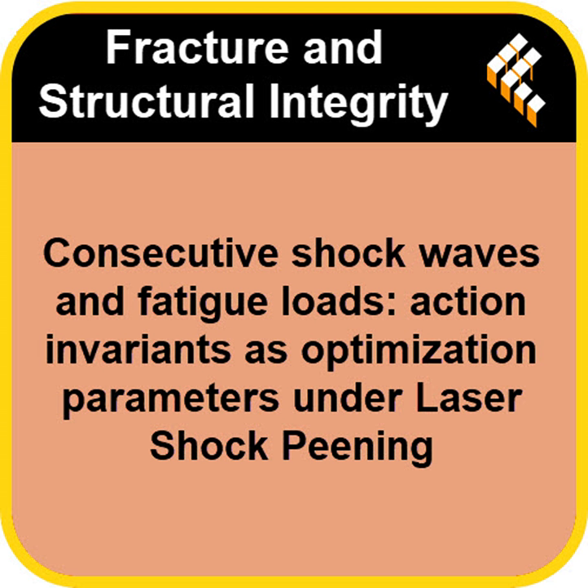And the example they gave was quite dramatic. An untreated VT6 sample tested at 460 MPa failed after about 500 million cycles. A laser-treated and polished sample not only survived much longer, 2.22 times 10^9 cycles, so over 2 billion. Wow, almost 4 times longer. But it did so at a higher stress level, 475 MPa. That's impressive. Longer life at higher stress. Clear proof the optimized treatment works. It really demonstrates the potential.